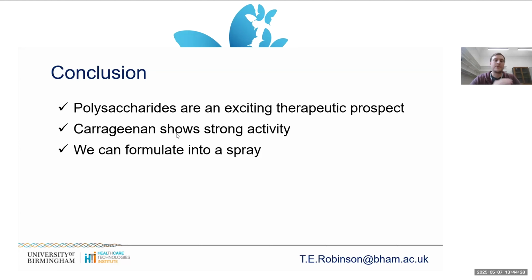I'm really sorry. But to give you an indication, for similar types of materials that we've looked at in the eye, a typical water-based eye drop won't last more than 30 seconds in your eye, whereas a gel-based eye drop will often last hours. So that's the kind of increase we can expect with some of these materials.